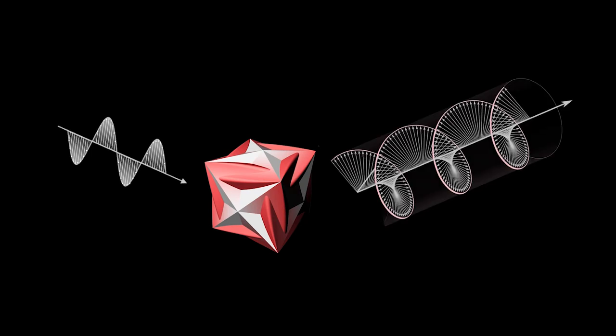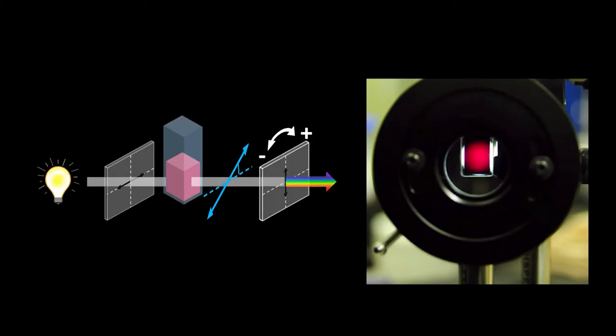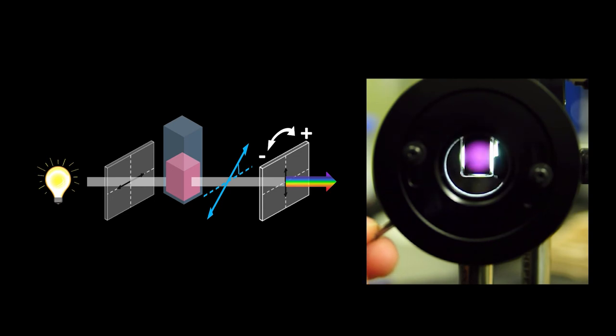This work was published in Nature, April issue, and featured as a cover. Because of its unique properties, it has a unique optical property: it can convert linearly polarized light into circularly polarized light, acting as a three-dimensional polarizer at the single nanoparticle level. It can add a phase component and also add polarization to individual light from individual particles.